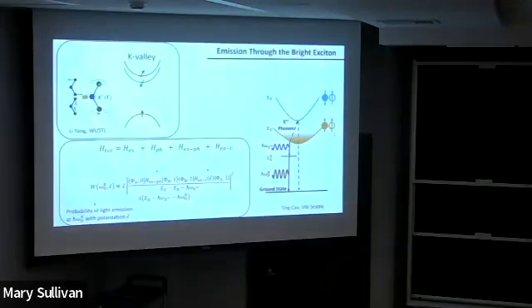So how do you do that? We were helped by Professor Li Yang here. He was able to help us calculate some of the phonon energy. Actually, one of the phonon energies matches very well with what we've seen, the 21.8 meV. So what happened is that you have these 2 phonon modes. These are 2 linear modes. And the linear combination of these forms the so-called chiral phonon mode, where one of the atoms is doing this motion, the opposite is doing this motion.